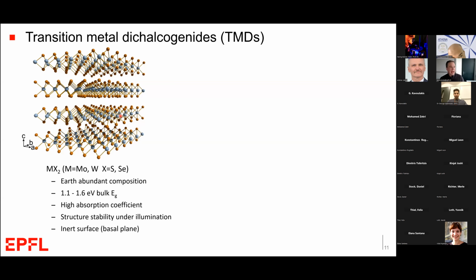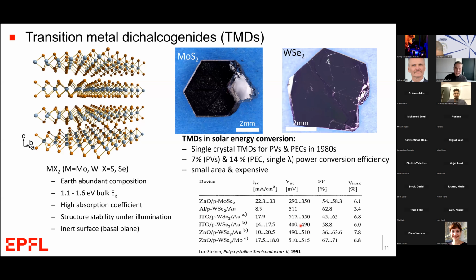So the high stability and the good band gap had led people in the 1980s especially to investigate these materials for photoelectrochemical and photovoltaic energy conversion. And in fact, those early works showed quite promising performance with conversion efficiencies close to 8%. But the drawback was that only single crystal devices could work. So polycrystalline devices made from these materials fared very poorly, and making single crystals proved very difficult over large areas. Here's a few examples of single crystals that you can even purchase of these materials, but they're extremely small. So making large area single crystals, and the difficulty to do that, basically meant these materials were probably not viable for large area solar conversion.